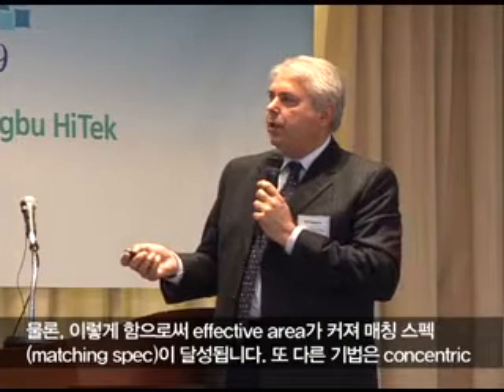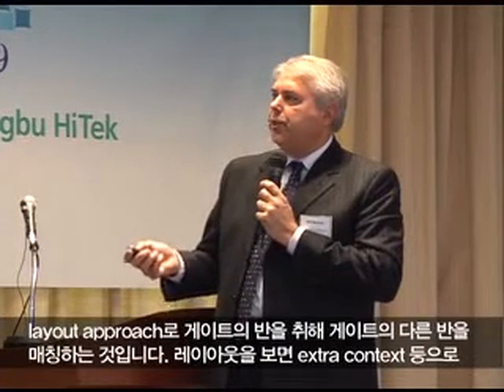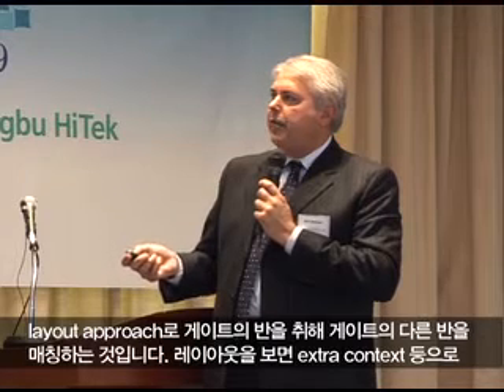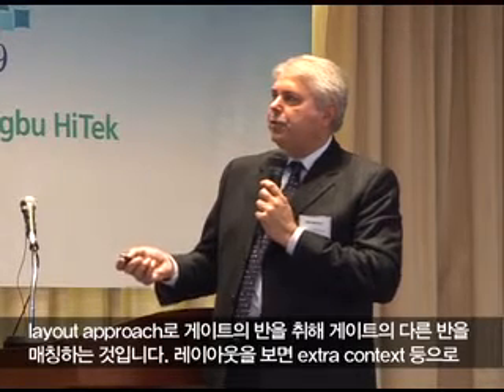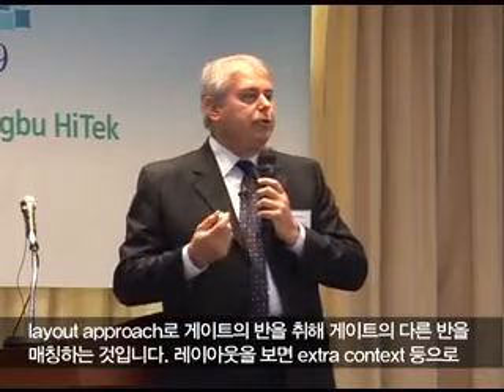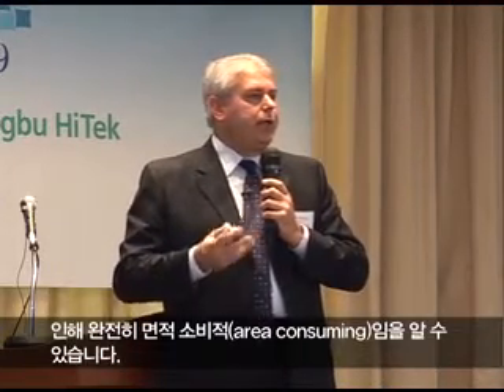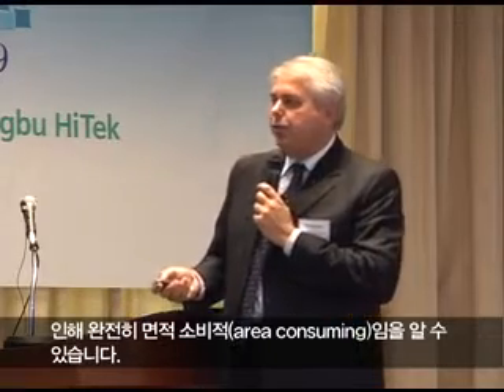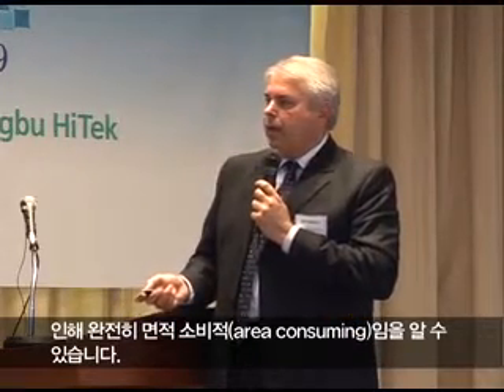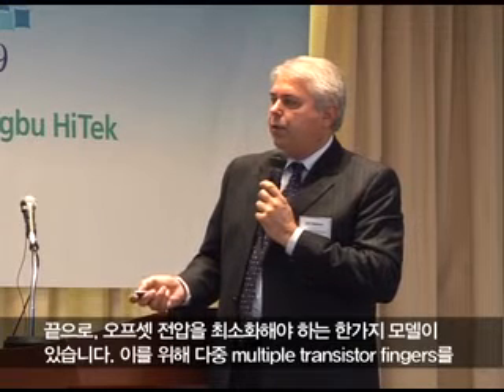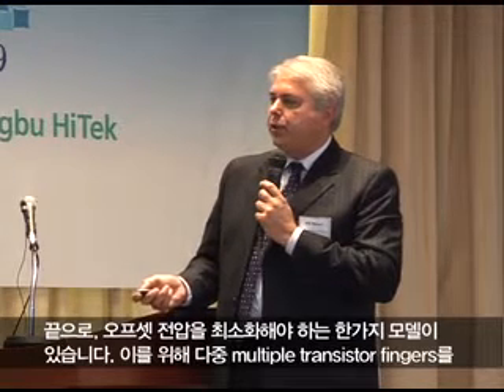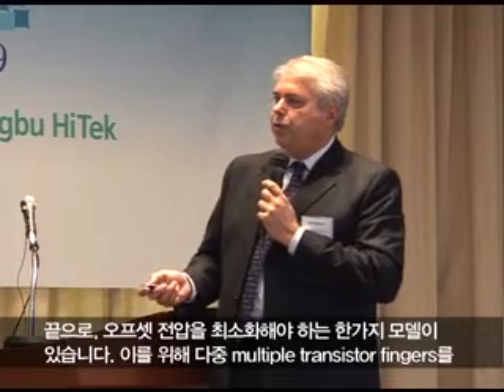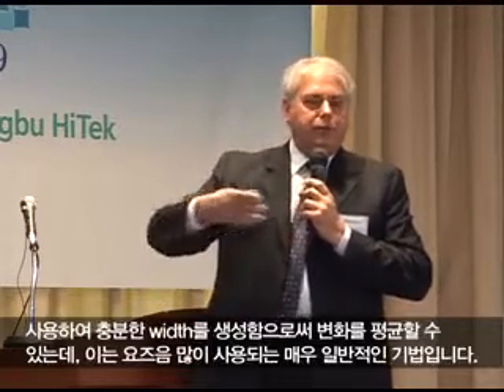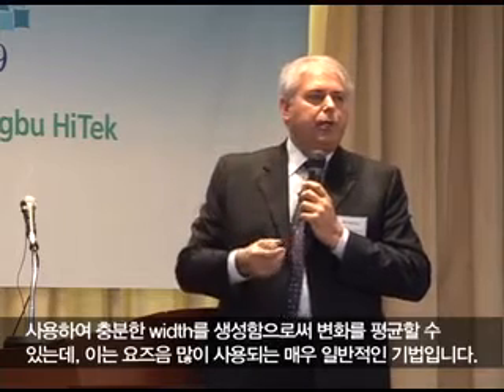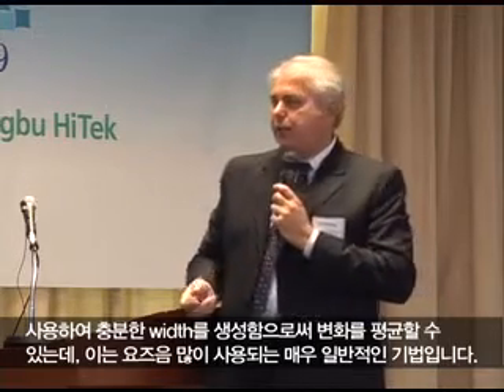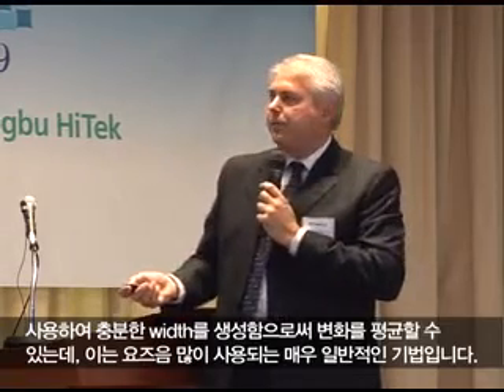Other techniques are to use common centroid concentric layout side approaches, where you take half the gate, the other half of the gate, and match these two against these two, and so forth. But these are also, if you look at the layout, quite area consuming with the extra contacts and so forth. In the end, there's one model that if you have to do the offset voltage minimization, you can use multiple transistor fingers to create enough W to average out the variations. That's a very common technique that's been used for quite a while now.